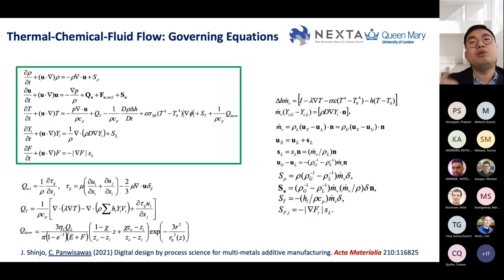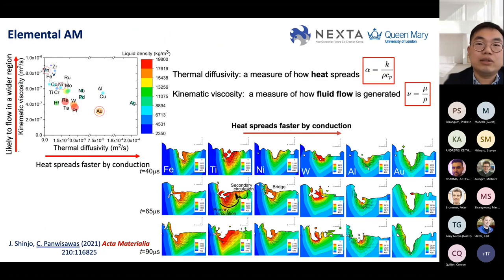So having said that, we want to extract some chemistry process characteristic actually using the thermochemical fluid flow framework that we propose in this Acta Materialia paper. And just don't want to go much into the detail of the equation. If you're interested in, please go to review some of the equation there. But more interestingly, we see some trend in this transition metal. If you look at the kinematic viscosity versus thermal diffusivity, one of them, the thermal diffusivity, definitely measure how heat actually spread onto your bed if you use a powder-based fusion process, for example. And kinematic viscosity measure how fluid flow is actually generated.